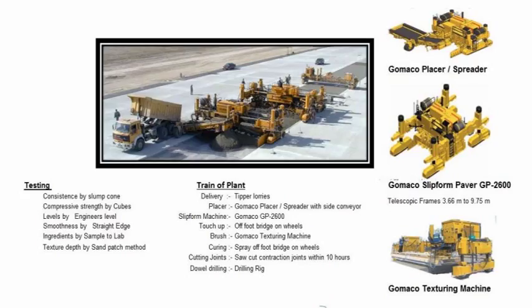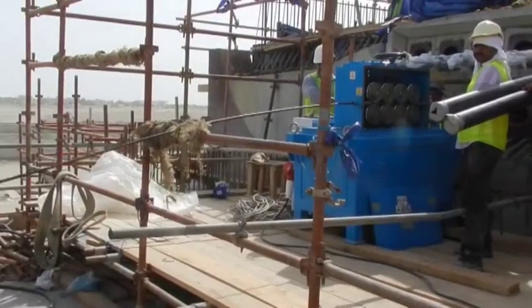Post-tensioning of bridge deck. The operation includes the fixing of the ducts and anchorages prior to concreting, the strand threading, stressing and grouting after concreting. Each strand is threaded into the duct one by one. The strand is fed into the strand pushing machine from a coil of strand contained on a reel trolley. The strand size is 15.7mm diameter and consists of seven wires with a total tensile strength of 1860 MPa. The tensioning is executed using two multi-strand jacks, one at each end of the deck.